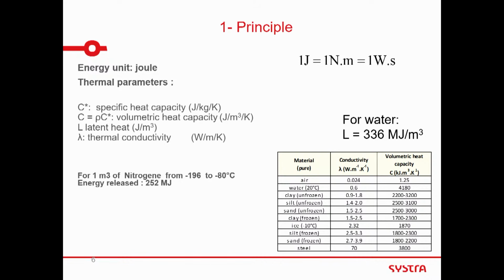So if you want the change in temperature of 1 Kelvin, 1 degree Celsius in this case, it's the same, per kilo, this is the unit of energy of joule that you need to put. This can be defined as a function of the kilogram or cubic meters of material. You have the change of phase of the water, which is called the latent heat. And you see that to change 1 cubic meter of water, you need this value, which is 336 megajoule per cubic meter of water.